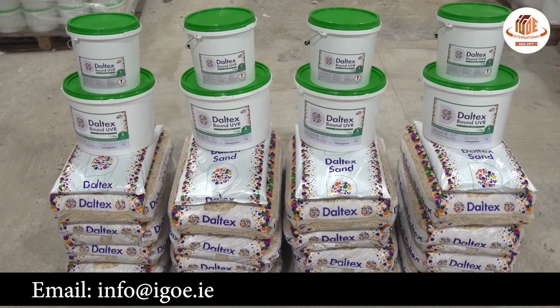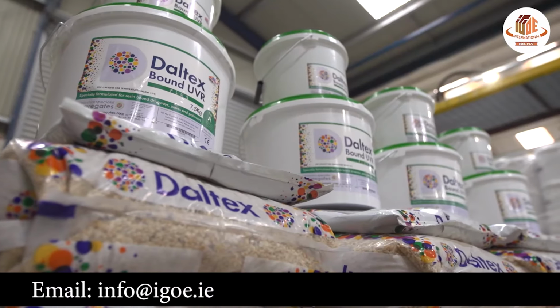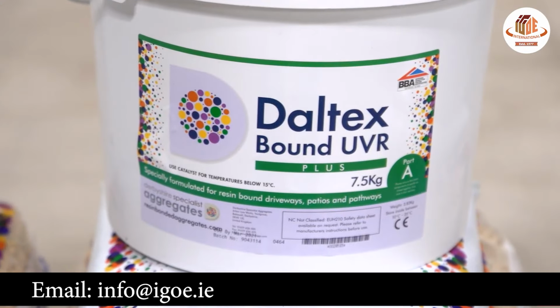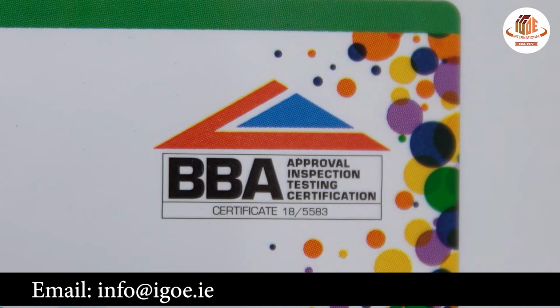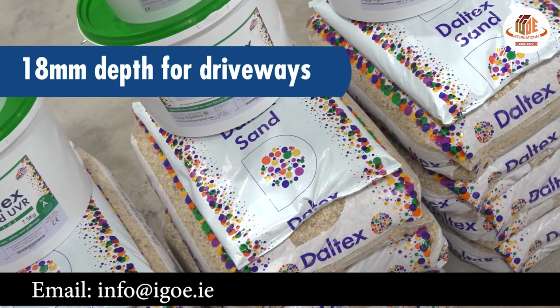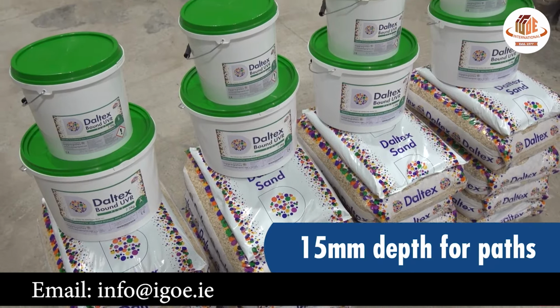Our experience and research shows that the correct ratio of resin to aggregates is critical to achieving a lasting, durable finish. To ensure the required tensile strength for application, we recommend a minimum depth for driveways of 18 millimeters. Pathways with foot traffic only can be reduced to 15 millimeters.